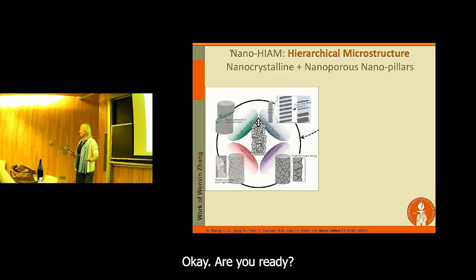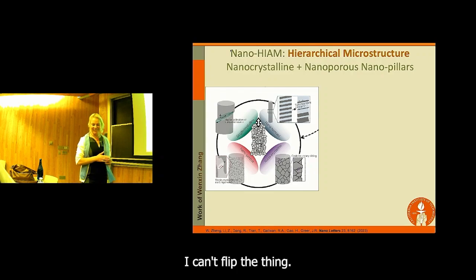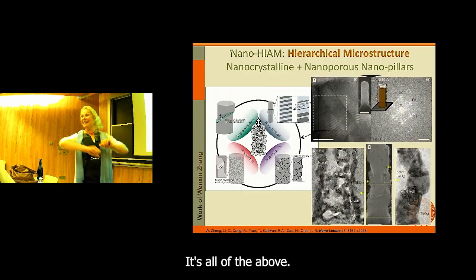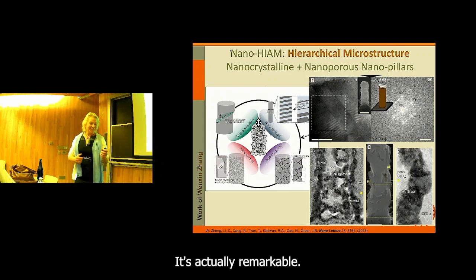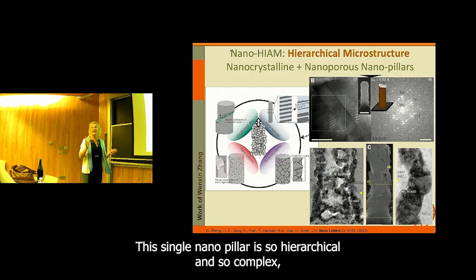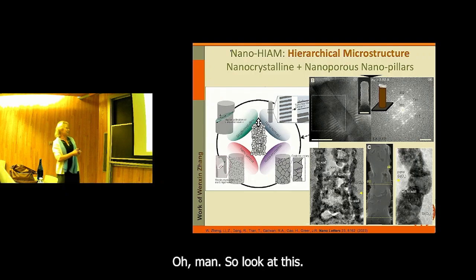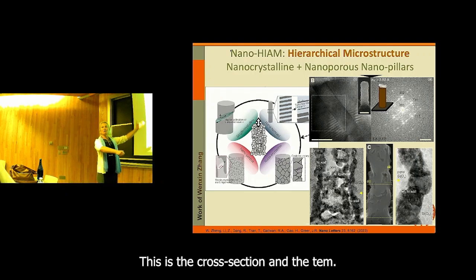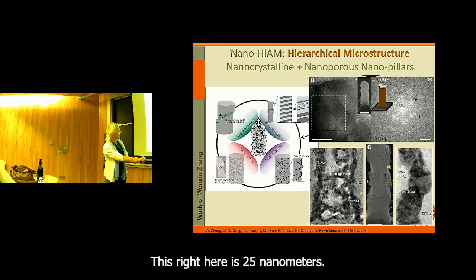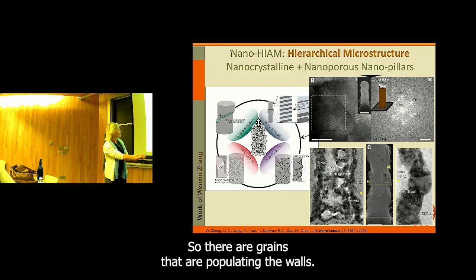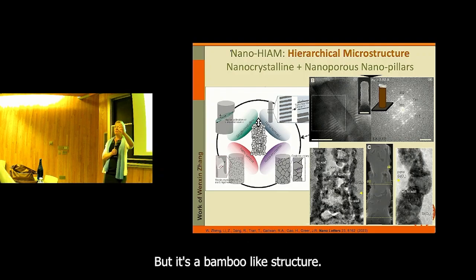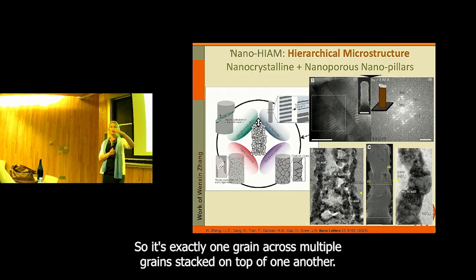Okay, are you ready? I can't flip the thing. It's all of the above. It's actually remarkable. This single nanopillar is so hierarchical and so complex in its tiny little body. So look at this. This is the cross-section in the TEM. This right here is 25 nanometers. There are grains populating the walls, but it's a bamboo-like structure, so it's exactly one grain across, with multiple grains stacked on top of one another.